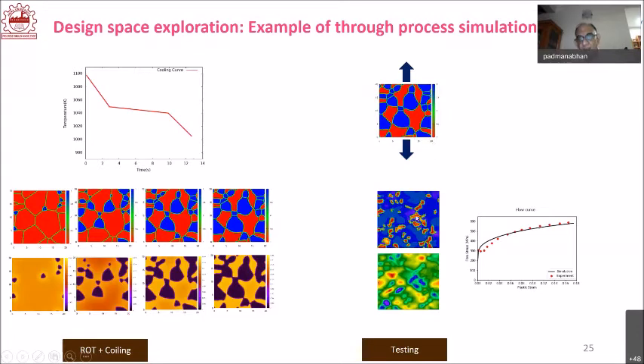And then, as I said, you only keep the martensite islands and remove the grain boundaries. So the blue one is the ferrite and this is the martensite. And then, with deformation, the alignment changes. You get this 45-degree orientation, which happens because of shear deformation. And then, as I said, the Gurson-Tvergaard-Needleman equation, for example, correlates the principal stresses that are operating, the nature of stresses, that is whether it is compressive, tensile, and so on. All these things are taken into account. And then, it will be possible for you to predict the property of yield stress. Yield stress is done in a fairly rigorous way. When it comes to UTS and percentage elongation, still a lot of empirical rules are used, which are experiment based.